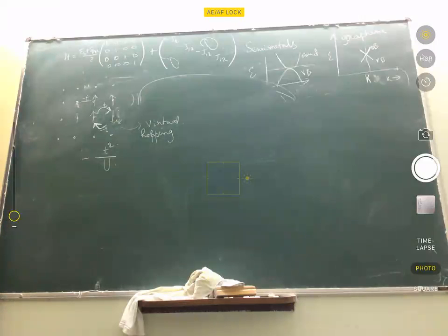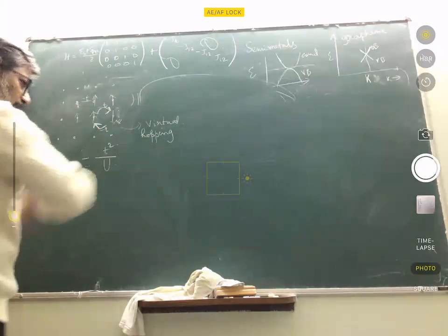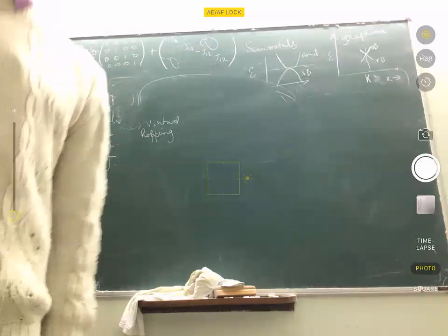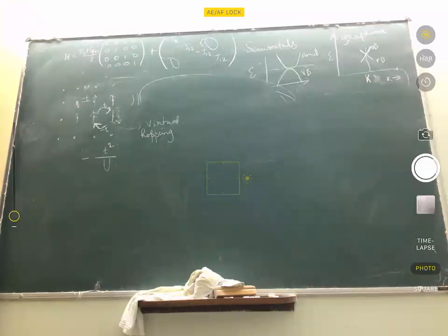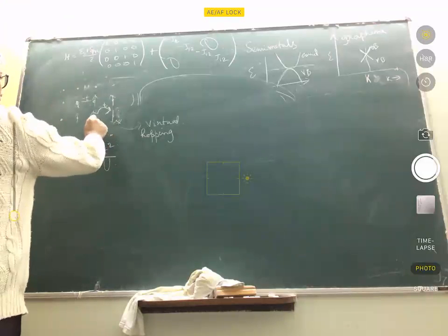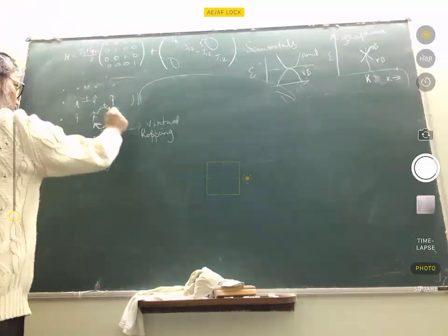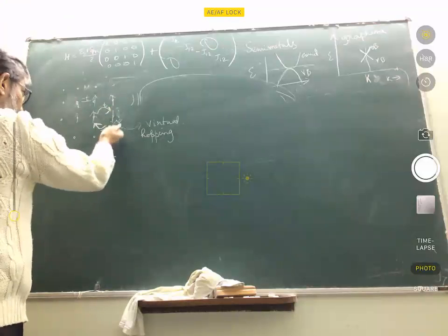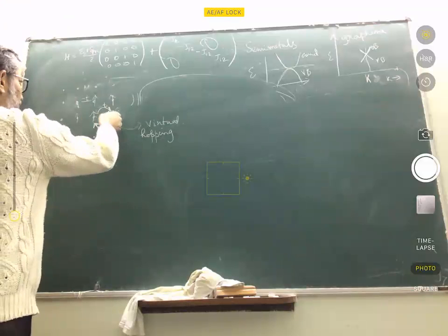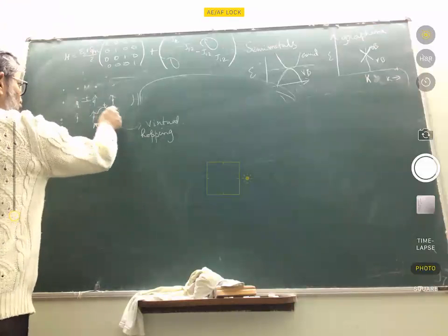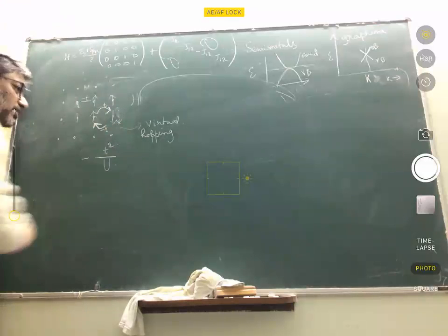So then what does that mean? This is like our kinetic exchange, right? We discussed kinetic exchange in the context of H2 earlier, but now we have put it on the model. So this is kinetic exchange of the Hubbard model. The important point to realize is that for that process to happen, for this electron to come here and go back, these two must have opposite spin.